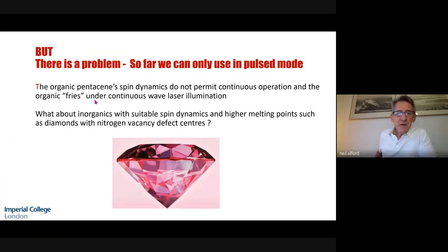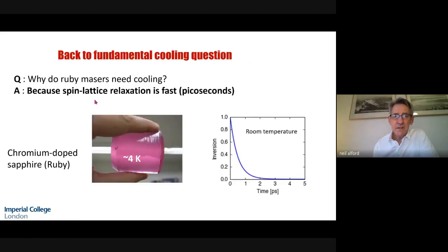Okay, so what about inorganics with suitable spin dynamics and higher melting points, such as, for example, diamonds with nitrogen vacancy defect centers? So let's go back to the fundamental question. Why do ruby masers need cooling? Well, because the spin lattice relaxation is so fast. And at room temperature, the spin lattice relaxation is less than a picosecond. So that is the problem. It's the real big problem. And so what we needed to do was to find inorganics with a much longer spin lattice relaxation.